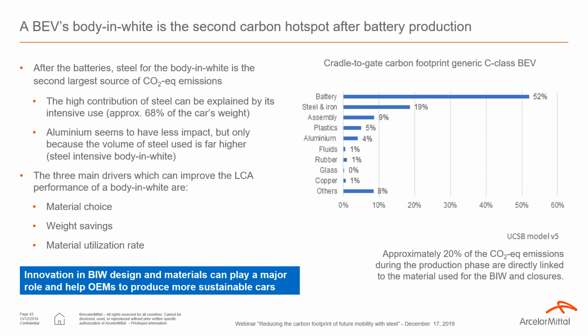So if we look at the material distribution on the battery electric vehicles, and especially the emission of CO2 equivalent related to the production, we can see that steel and iron is ranked at the second position. So it means that it's the second hotspot. Of course, we have to keep in mind that steel and iron represent more or less 60 to 70% of the car weight, and that explains this high position, especially if we compare with aluminium at only 4%. Here we have to take into account that steel is by far more used.